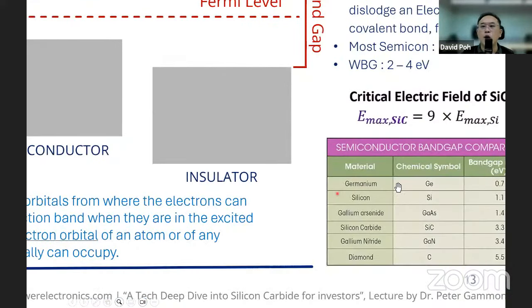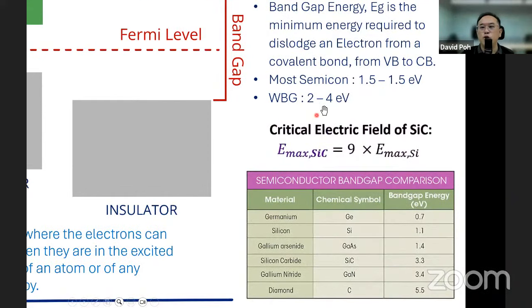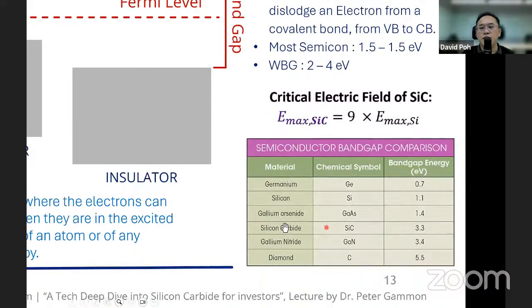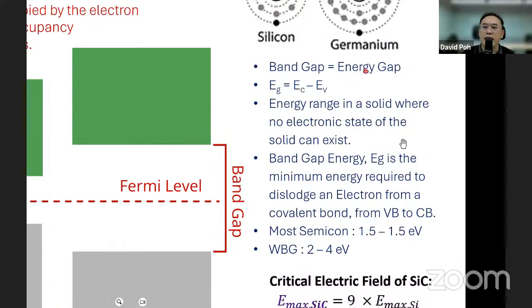Now, in between these, with a wide band gap energy of between 2 to 4 electron volts, sit these very special compounds called silicon carbide and gallium nitride. Now, of course, there are many other compounds that fit into this, but those that are very well known and easily producible are these, for example, here. All right. Now, you can study the electrical properties later on from here. But one of the things that I want to highlight is the critical field of the wide band gap semiconductor, which is denoted as the Emax.